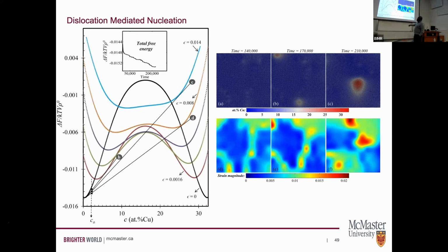You could also take a look at the strain map. So where are the dislocations and concentration? What are they doing? Because if I'm saying that dislocations are mediating, a dislocation tends to distort lattices and introduce strain. But then you could also do a simple free energy analysis, where the dotted line is where I'm assuming that my solid is strain free. And then I've introduced a strain parameter. Again, my double well that had this energy barrier slowly, as a function of strain, is becoming a single well. I.e., again, I'm removing the barrier associated with that transformation.